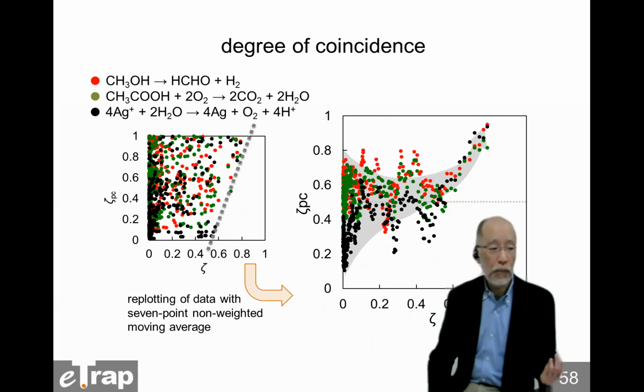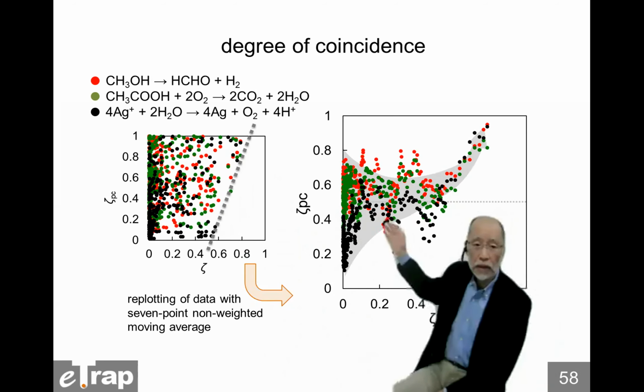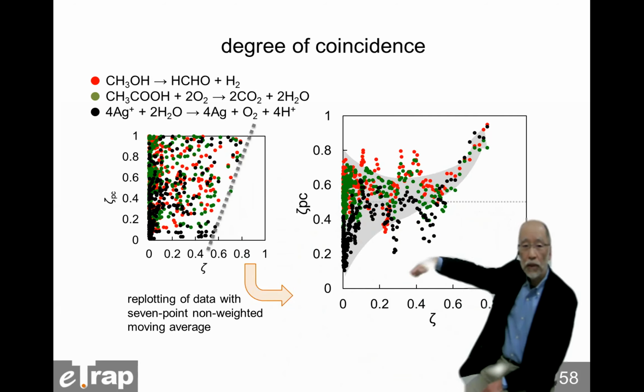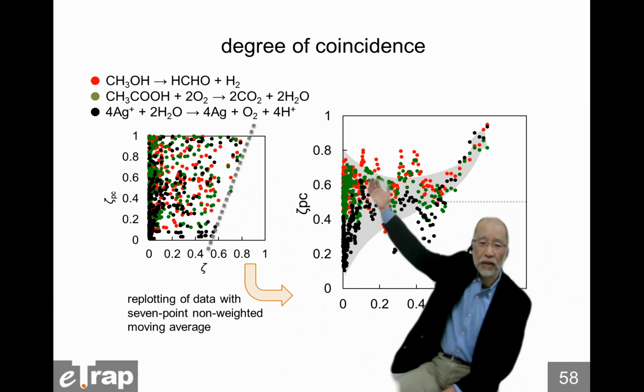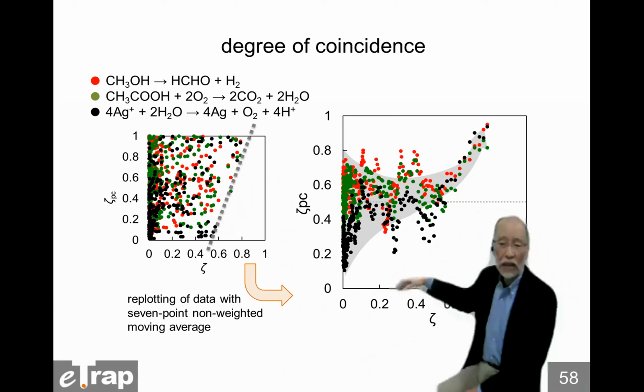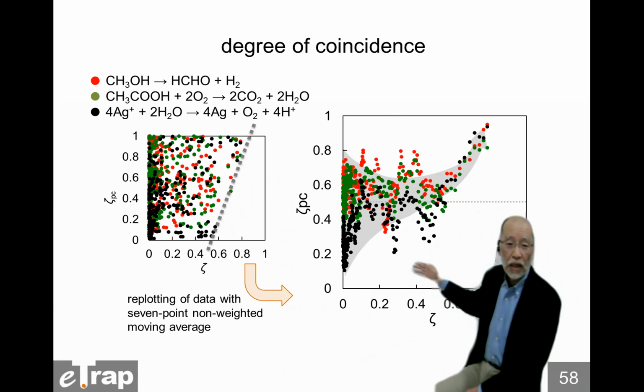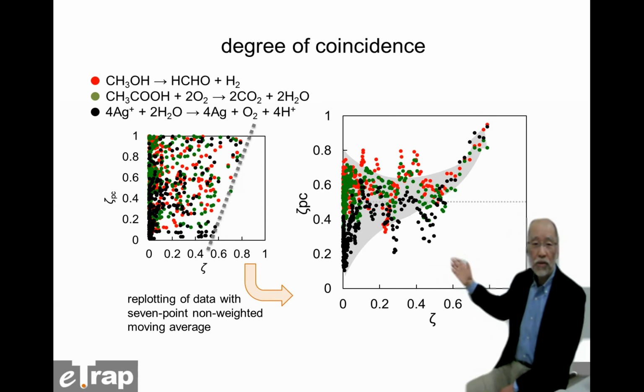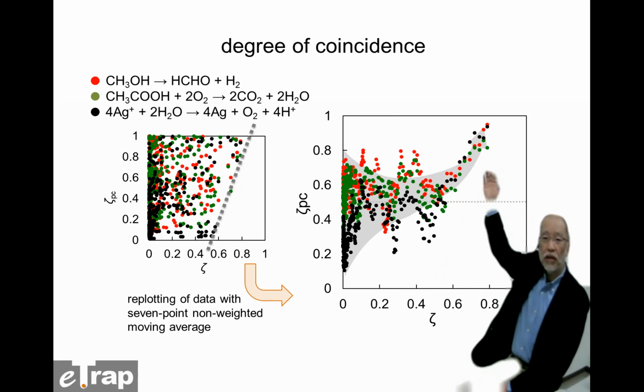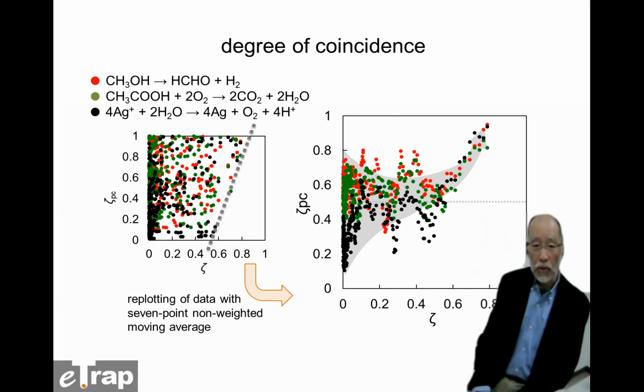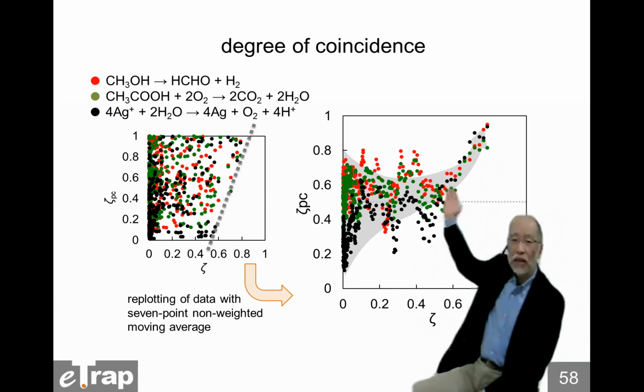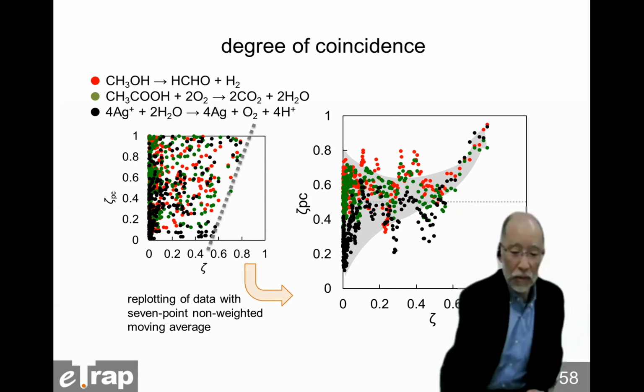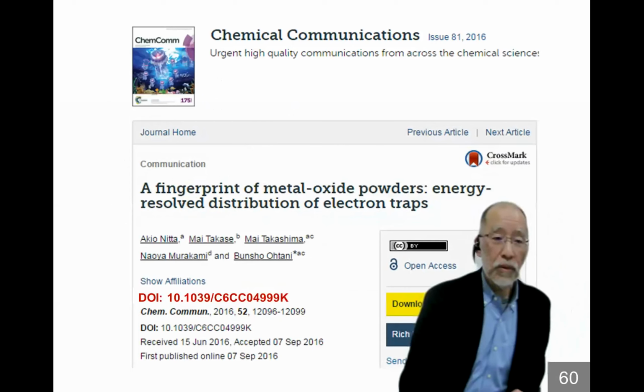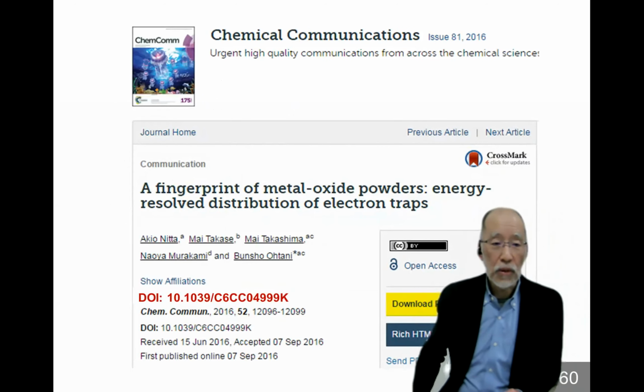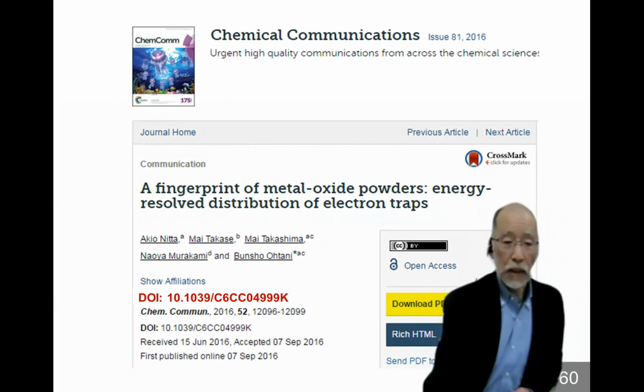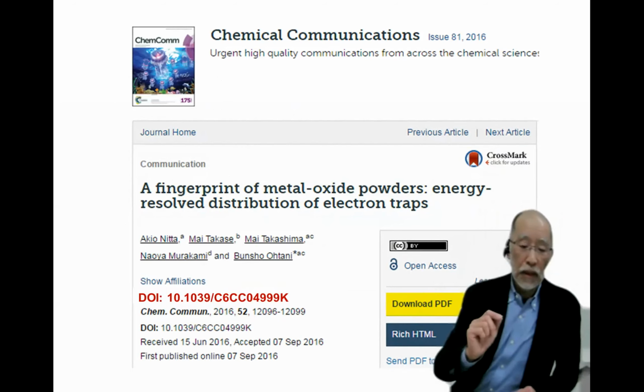And by taking the moving average, below a zeta value of 0.6, the data is very scattered, so accidentally the same photocatalytic activity or accidentally a low degree of coincidence of photocatalytic activity. However, if the zeta value is higher than 0.6, the zeta PC increases to give almost 1 at zeta equal to 0.8. Yes, so that means similar titanium oxides give similar photocatalytic activity. And we love this elephant plot. This was first published in Chemical Communications in 2016, and it is open access, so you can download it freely.